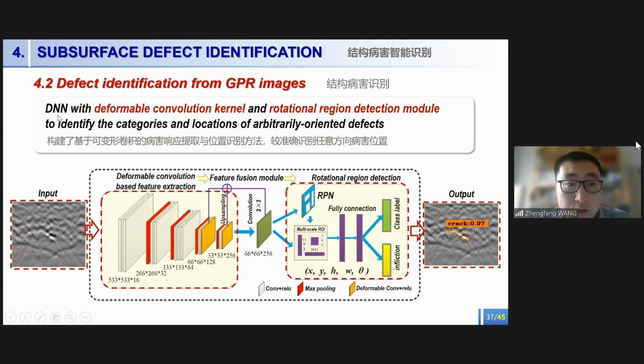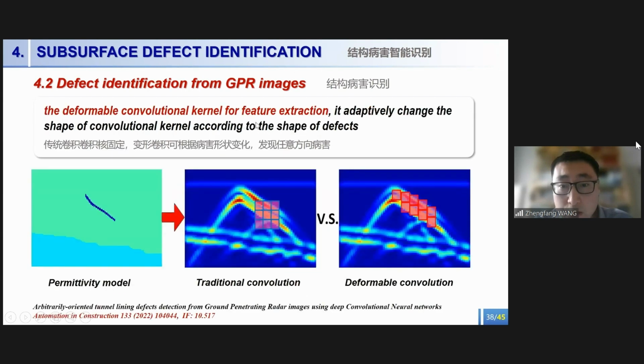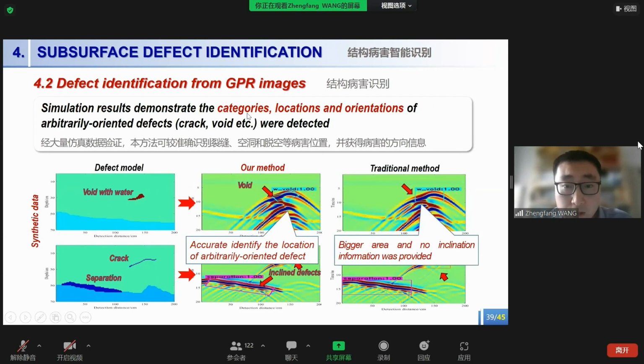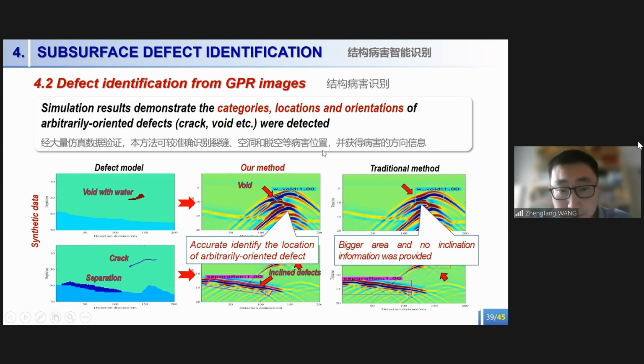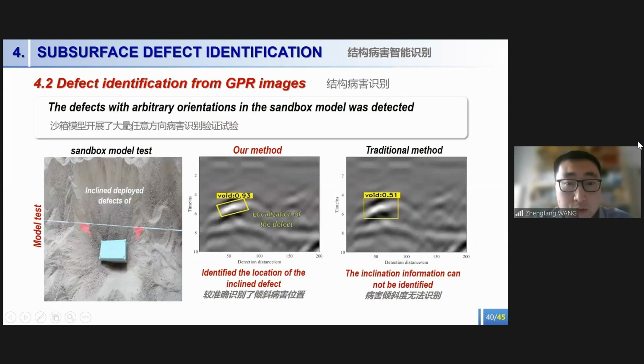The key is we used a deformable convolutional kernel for feature extraction. It can adaptively change the shape of the convolutional kernel according to the shape of the defects, not like the traditional kernel, which has a fixed shape. The simulation result demonstrates that not only the category and location, but also the orientation of the arbitrarily oriented defects can be detected. Then the method was also tested by the sandbox model, and it can provide us the location and orientation, as well as the class label of the defects.